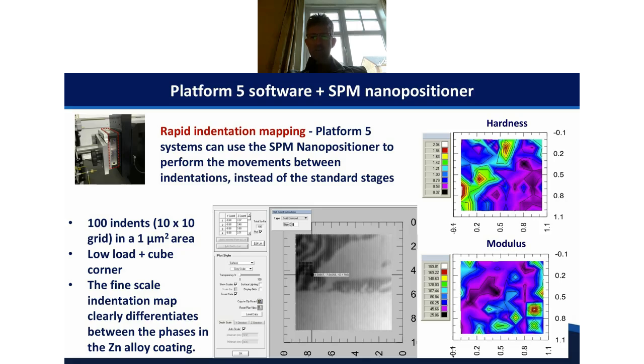So obviously, if you make the indents too big, then they're just going to overlap. So in this case, Adrian switched to a very sharp cube corner indenter, very low load measurements. And when he does that, interestingly, he can very nicely reproduce the different mechanical properties of the different phases in this material. And it's quite nice in this case because you can see that the hard phase in this system is actually the least stiff as well. So you can see that these are true mechanical property measurements. They're not being influenced by the topography of the system.